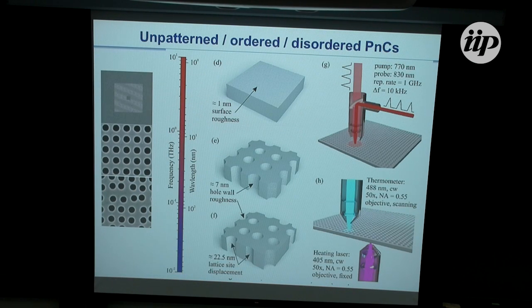So this is just for illustration, the frequency range going to 10 terahertz, and in wavelengths going from 100 to 1 nanometer here. So that's where we are pretty much. And experiments are done on, well, we measure the surface roughness, we obtain an estimate of the wall of the hole's roughness of about 7 nanometers in worst case, and the lattice displacements in the disordered structures can be up to about 22 nanometers. So like 10%, 7% of the period.